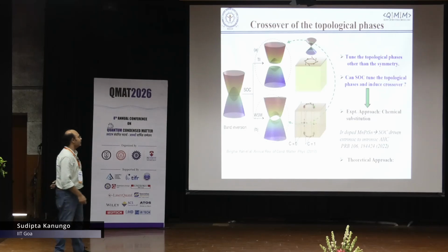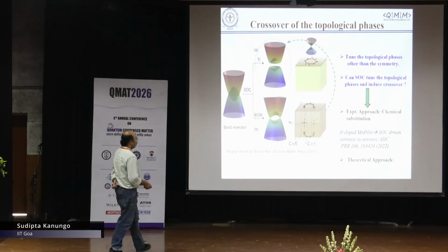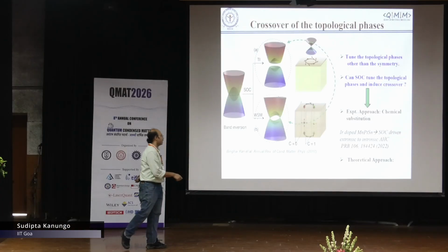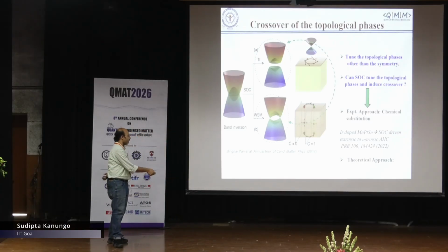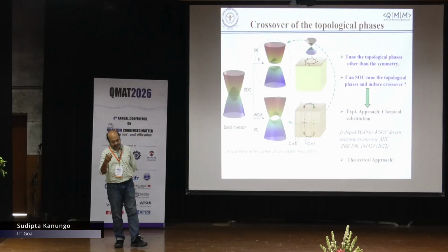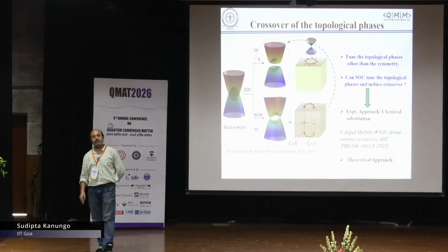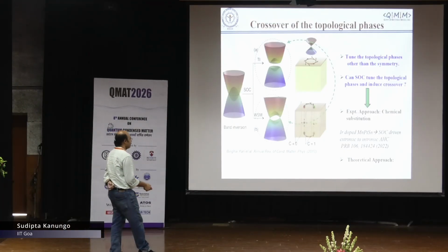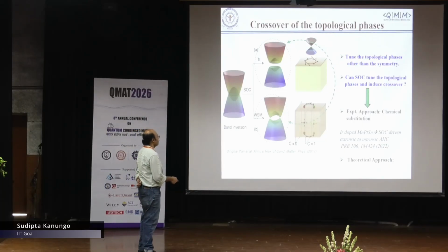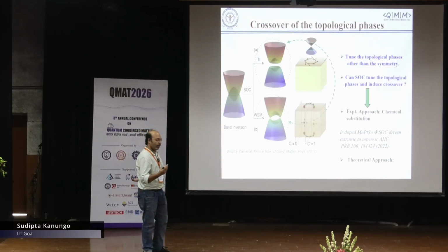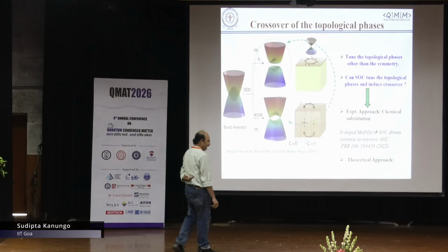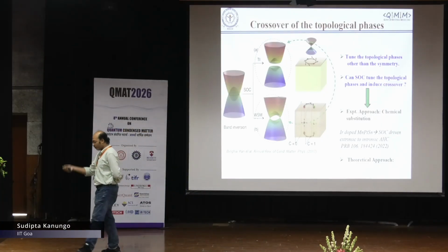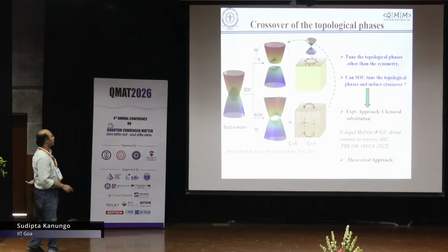technically I can tune the strength of the spin orbit coupling. We also did this with an experimental colleague, and we showed that we can enhance the extrinsic to intrinsic anomalous Hall conductivity by this chemical doping. However, we can also do it theoretically, since we are working at an ab initio level, we can tune the interaction as per our own wish.